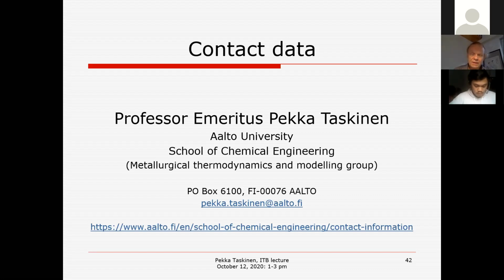Those heat exchangers, which were actually preparing that high temperature oxygen air mixture, were blocked so often, and that is why that has been abandoned for probably 20 or 30 years. Very few smelters are using heat recovery for heating the inlet material. It was actually the issue of the Outokumpu patent originally in 1948 or 9, when they patented this flash smelting process, preheating of process gas, but it's not used anymore.